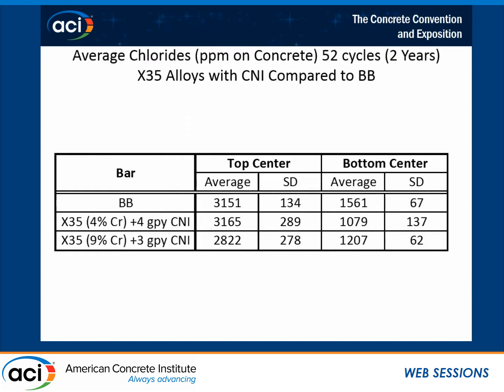Now, we also did some extra work looking at X35 bars with calcium nitrite, and we have known from the past, some studies have shown that calcium nitrite improves the bond strength of rebar. So I said, what would happen if you had a high-strength rebar and you put something in it that helps improve bond? Here's the black bar information from a different set of series. It's the same series, and you can see the average at the south is pretty high at the top center, at the bar level.